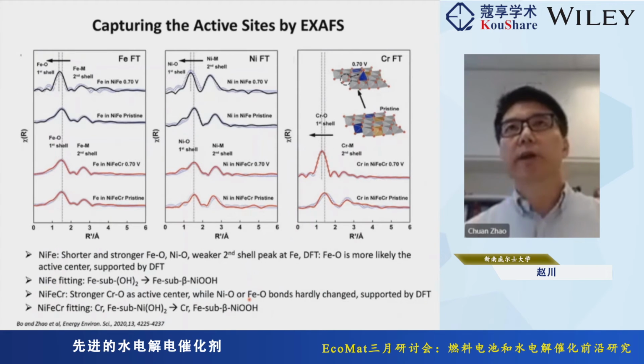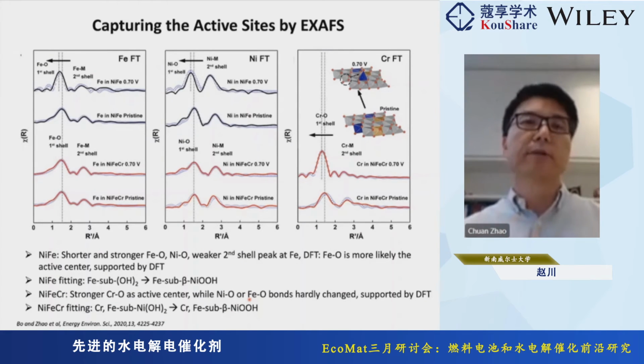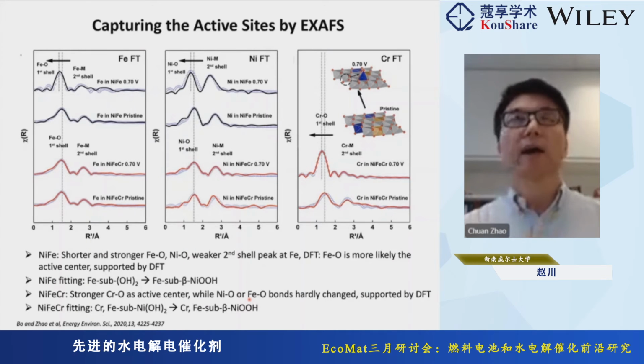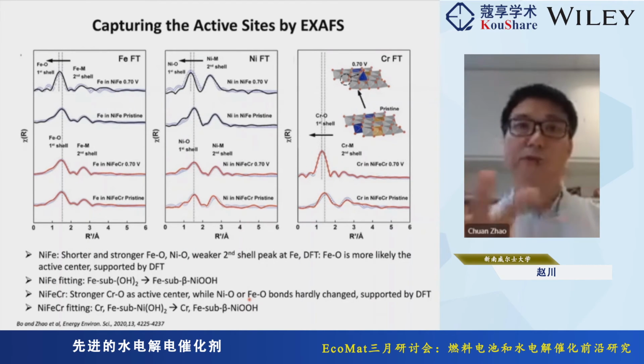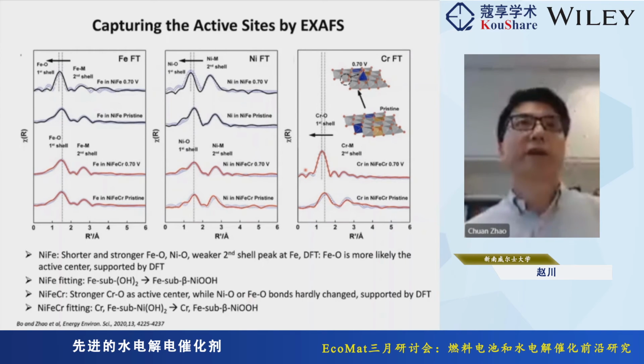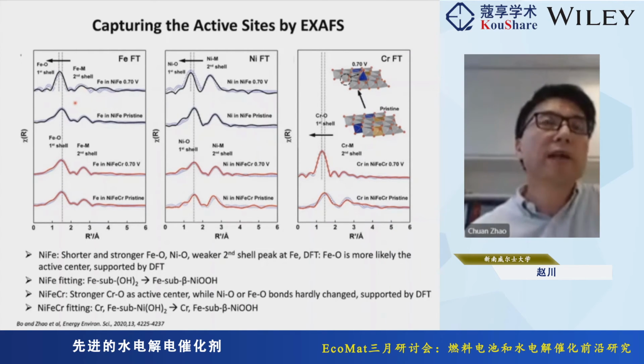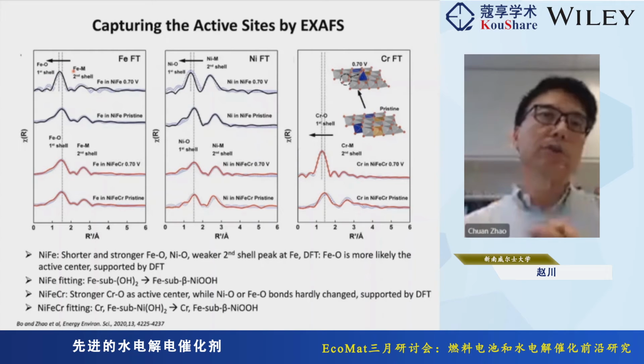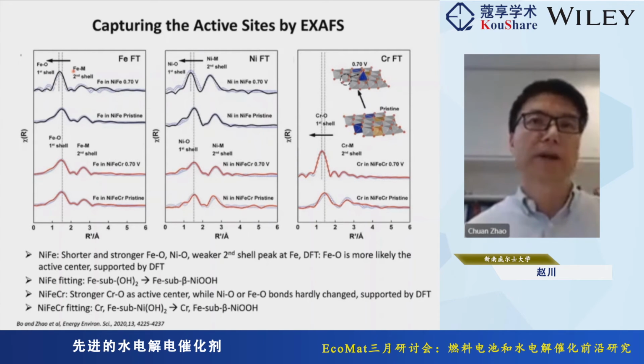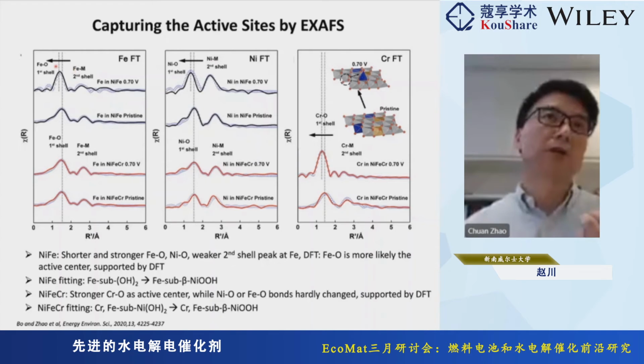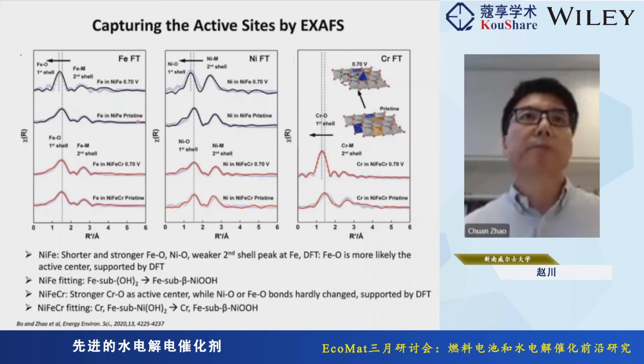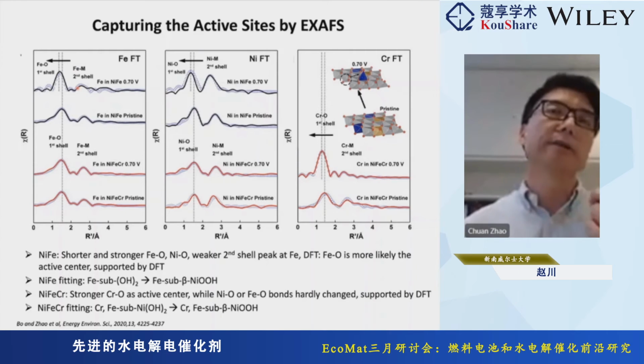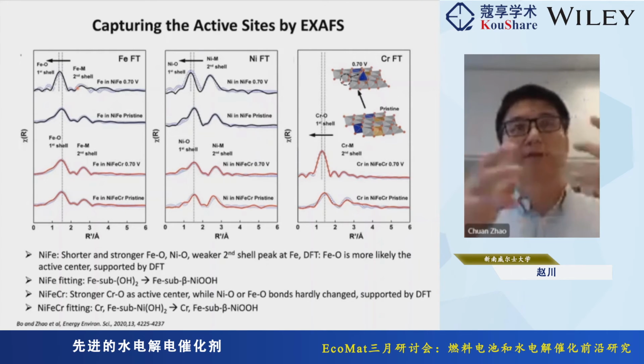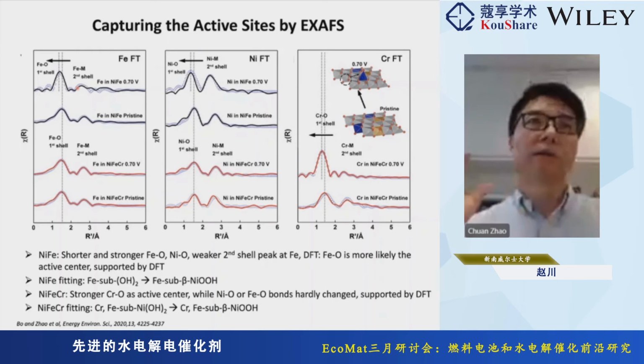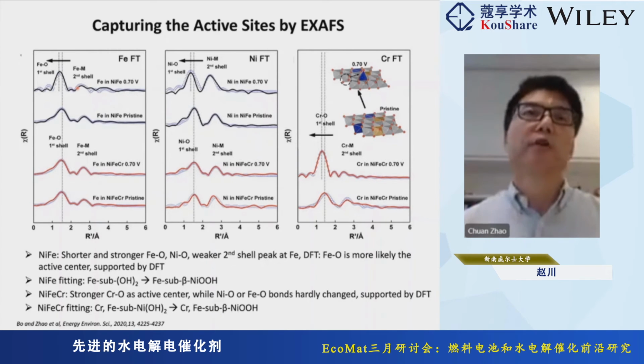And then we use EXAFS to understand better the activity, how the catalytic reactions distribute between the three metals. And what we can find out is, with nickel iron, when we apply potential, there's a decrease of the nickel-iron bond and both the nickel-oxygen and also the iron-oxygen. But compared to the second shell peak, iron has a smaller, weaker peak, which suggests there's a more disordered structure around the iron, and iron is more likely to be the active site.